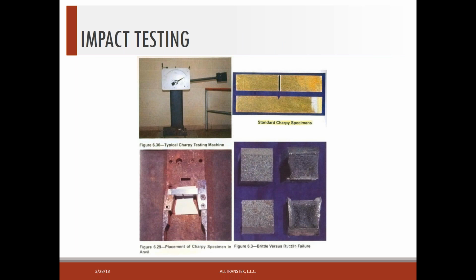Okay, we mentioned the requirement for notch toughness testing. This is not the only way to test this, but the typical way that we would test notch toughness is with the Charpy V-notch test. At the upper left-hand corner, you see the actual impact testing setup. And if you look at the right of that picture, you see what's called a hammer, and it's brought up into the loaded position. That hammer will actually be released, and it will strike the impact specimen with a certain force. And the force that it takes to break that particular Charpy specimen is measured in foot-pounds.